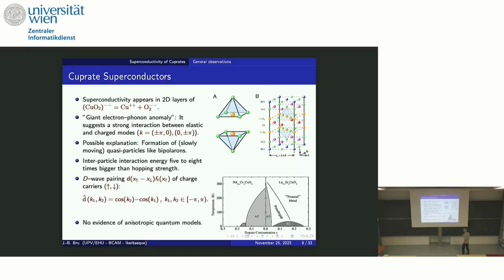And rapidly, the antiferromagnetic phase disappears, and after a certain doping you get a superconducting phase. So it becomes a superconductor. And there is the critical temperature of the superconductor, and then there is also something else which happens, which is a pseudo-gap regime. My model is more designed for this regime than for the superconducting phase itself.